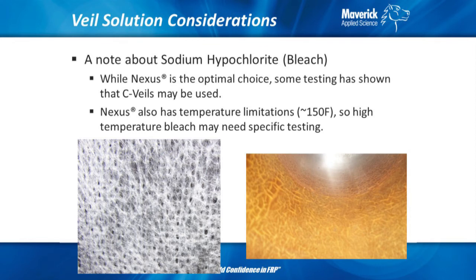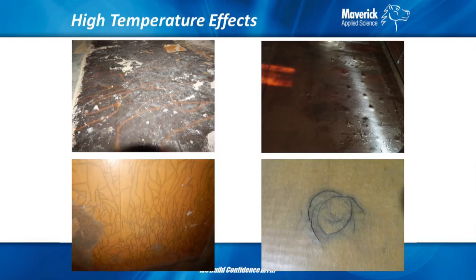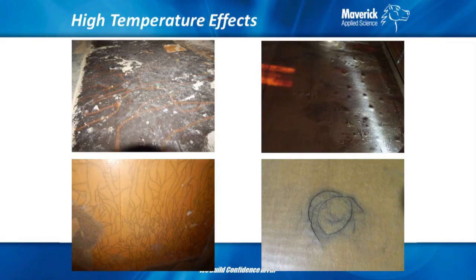And this is where, in the picture on the right, we see some crazing of the liner, a little bit of thermal shock, where if it's over 150 degrees Nexus doesn't work very well. So these are just some pictures of the realities of high temperature effects on these components. It might be poor veil selection, or an excursion temperature that wasn't anticipated. It's kind of hard to see, but in your handouts you can see a lot of fine, hairline spider cracking with even some open blisters. To me, that tells me it's a high resin content.